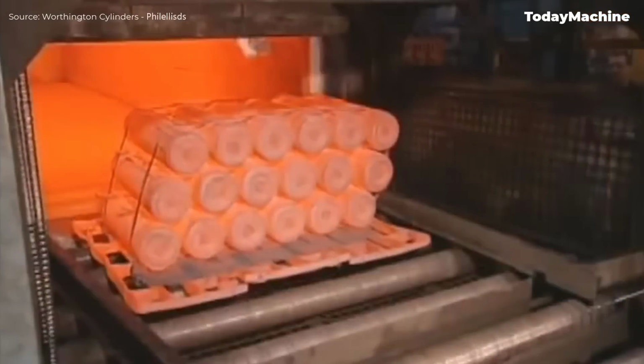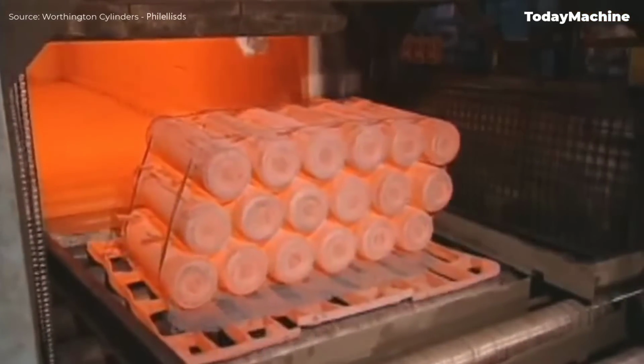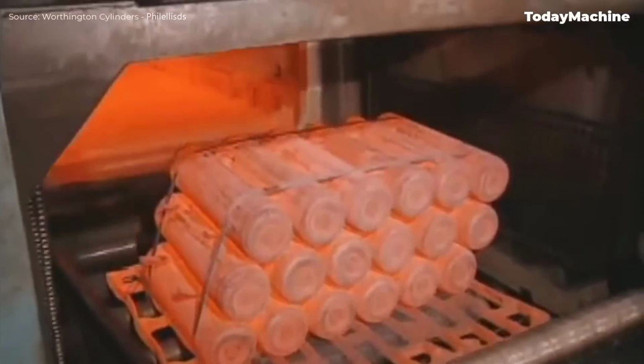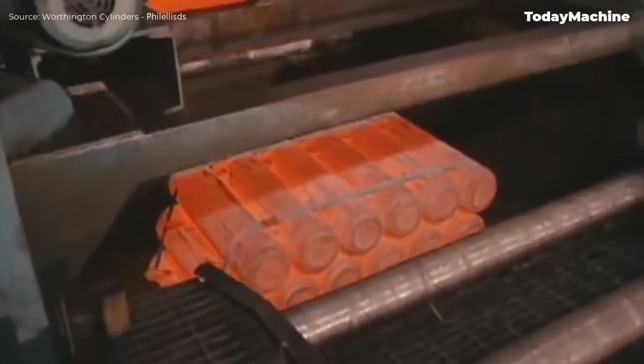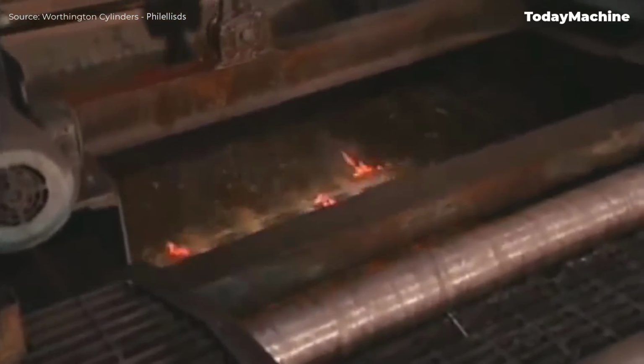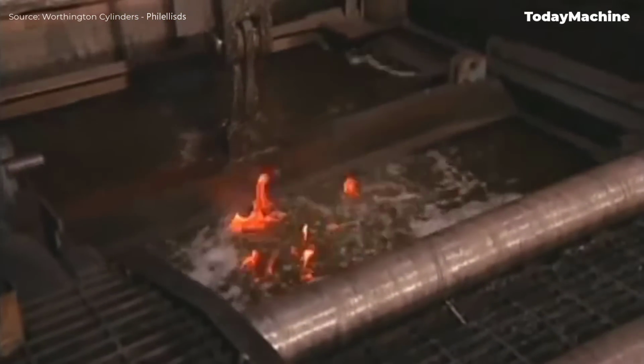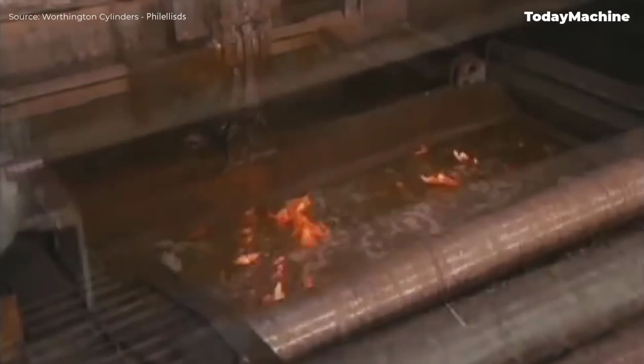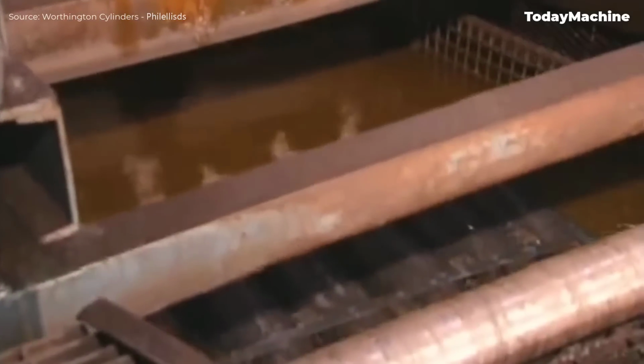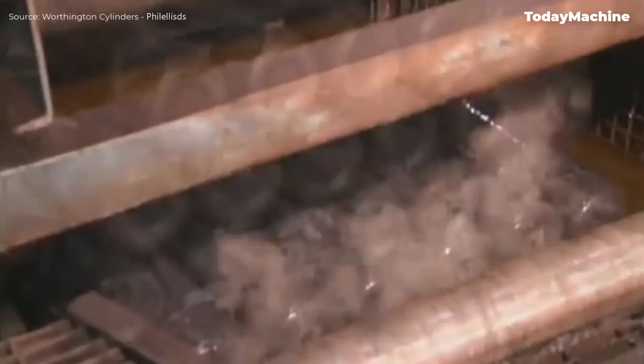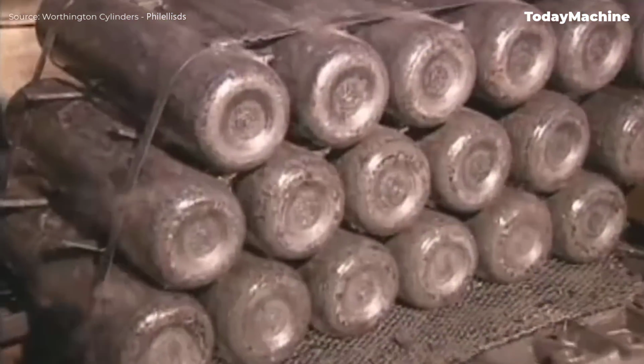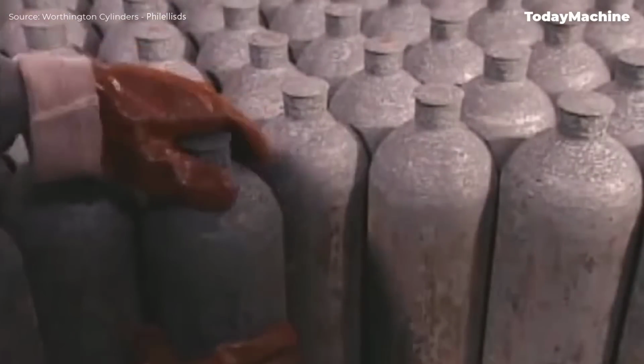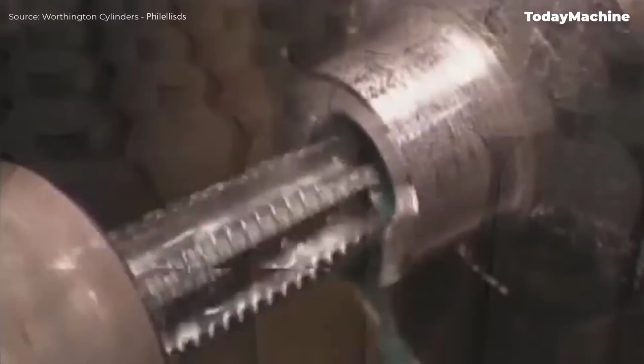The cylinders are completely closed before heat treatment, minimizing interior oxidation and ensuring a smoother surface finish. The cylinders pass through a direct-fired furnace, followed by an aqueous polymer quenchant, and then a direct-fired tempering furnace. These computer-controlled furnaces ensure optimal and consistent mechanical properties to meet regulatory and customer requirements.